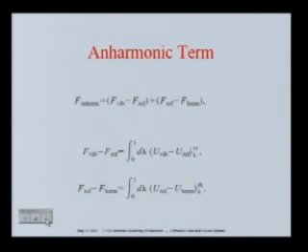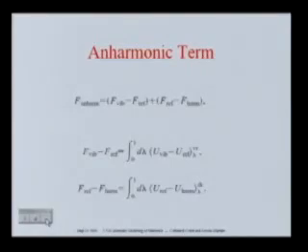So you would do molecular dynamics or Monte Carlo simulations to sample as much as possible a set of representative microstates, but it tends to be very expensive. So there is a very useful trick that is often used in order to calculate this anharmonic term. Remember, the anharmonic term is nothing else than the overall vibrational free energy minus the harmonic term.